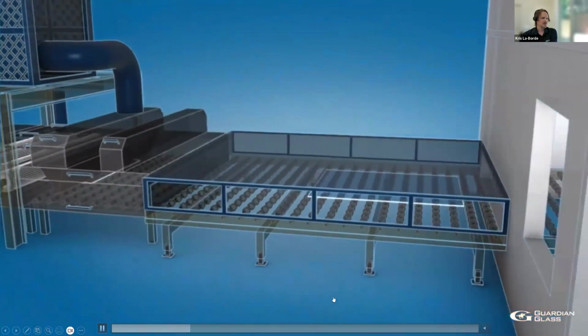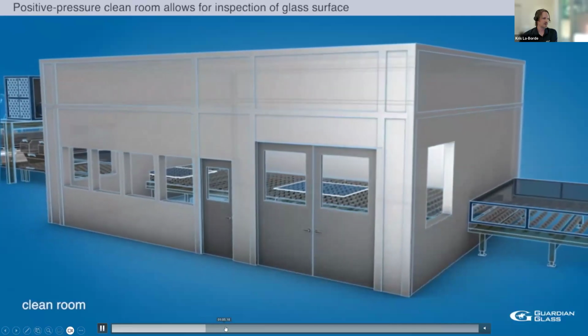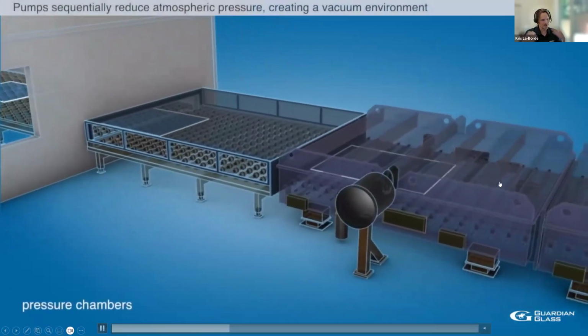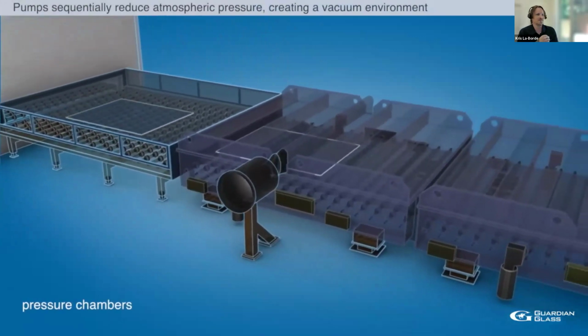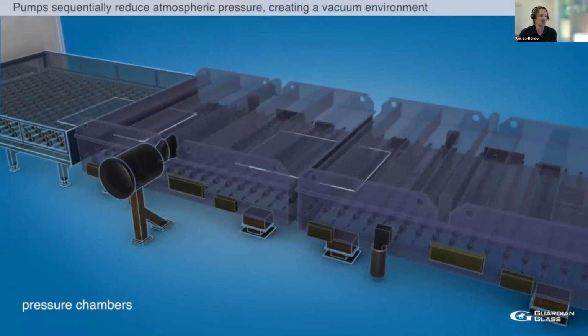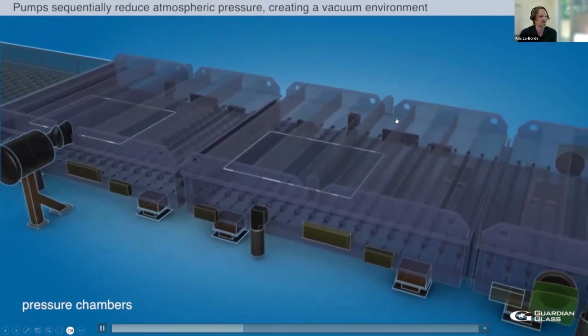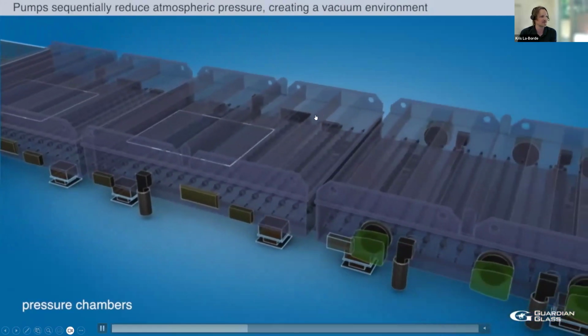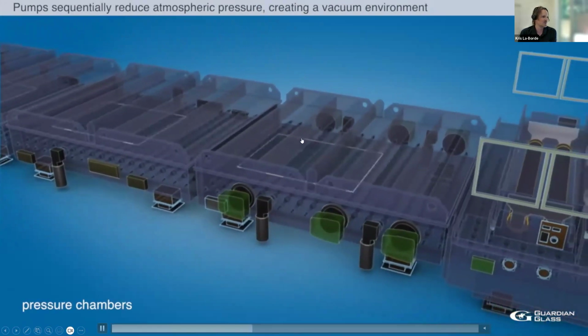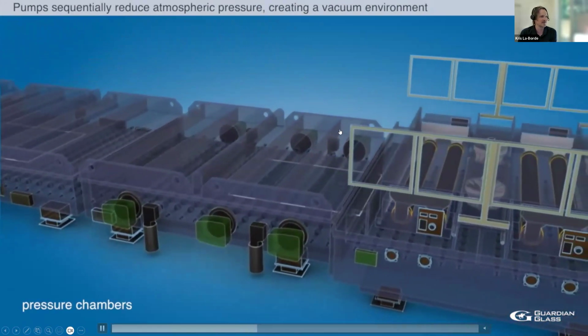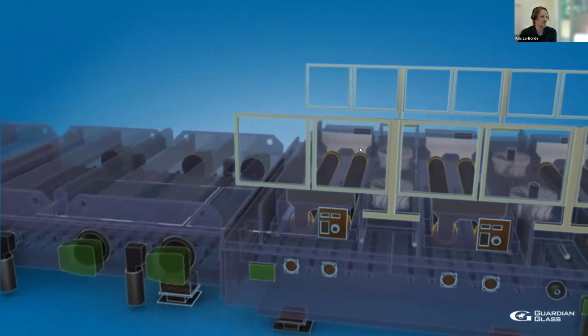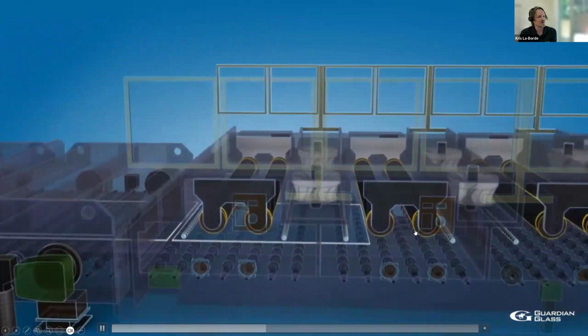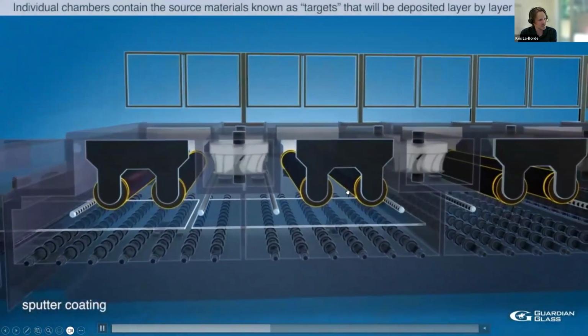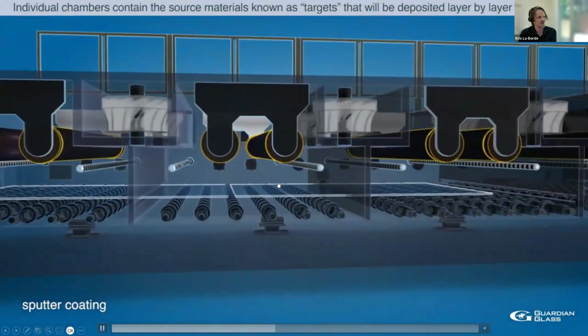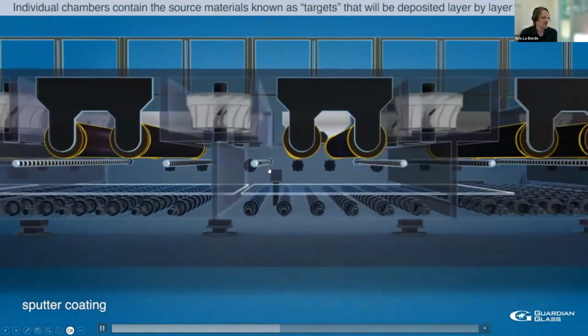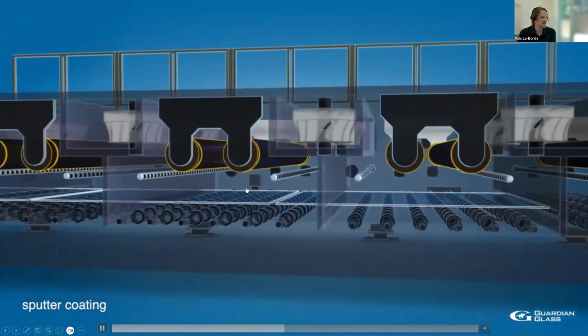So it gets washed, and then this is the important bit. It goes into a vacuum, so we suck out all the air, and we actually statically charge these cathodes. They're almost like printer rollers, and each one of these rollers is a chemical element. And the silver is the workhorse. We'll also have other chemical elements that are kind of the antidotes to what we don't want silver to do. So you statically charge all this, and then you fire ions at these charged cathodes, and they will be attracted to the glass surface. So I'll probably let this play for this little clip and then move on.